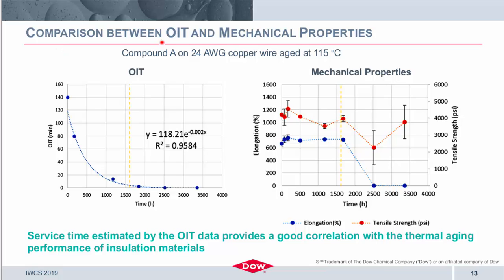So when we look at comparison between the oxidative induction time and the mechanical properties, here in this case on compound A, in the 24 gauge copper wire samples, aged at the highest temperature of 115 degrees C. What we see here in comparison of the OIT to the mechanical properties is that for the OIT value, we dropped to our 5-minute point, which was considered the failure time in our study, at around 1600 to 1700 hours.